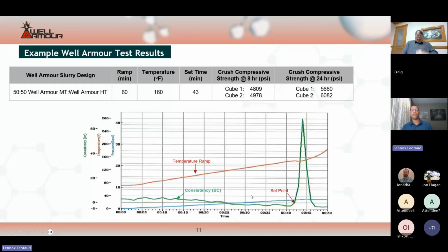Here's another example of a set time test that was done at up to 160 degrees. The ramp time was 60 minutes, and you can see the set point here occur right at the 43-minute mark. Also provided here are some compressive strength development results. You can see that 8-hour compressive strength values are around 4,900, and 24-hour compressive strength values are around 5,600 to 6,000 psi. So that gives you an example of the compressive strength build of the Well Armour product or system.